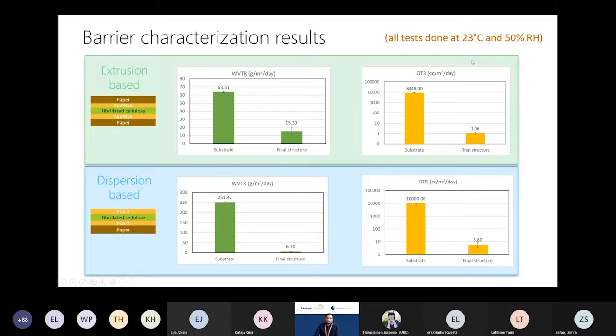Then the oxygen transmission rate is interesting because here we were almost above the measurement limit, and in the final structure, with this fibrillated cellulose coating acting as an oxygen barrier layer, we were able to bring it down to 1, which is within our target that we had set out in the beginning.